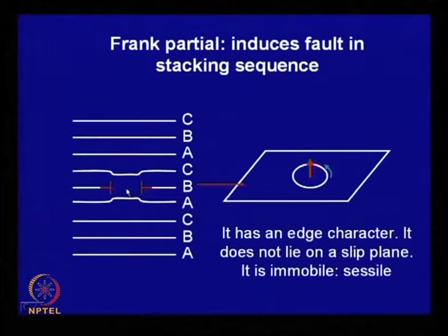So, this part has been moved over here, by this displacement, and you do not come to occupy that similar A site. So, basically we can calculate this Burgers vector. This Burgers vector's direction is perpendicular to the close-packed plane, and the close-packed plane in this case is 111, and this Burgers vector is equal to a/3 <111>,